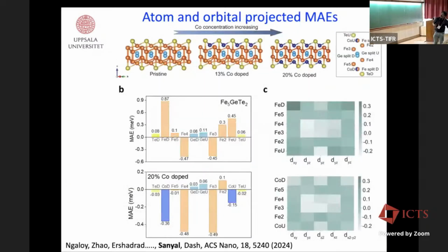We wanted to find out the reason for that, and that's why we calculated the atom-projected magnetocrystalline anisotropy. This is the result for the pristine system, and this is for a 20% cobalt-doped system. You see these positive and negative numbers; overall, if you sum them up, it gives you an out-of-plane easy axis of magnetization. But when you dope cobalt, for example, this iron D site here, when it is replaced by cobalt, instead of positive it goes to a negative direction. So it shows that cobalt doped at this site has an in-plane anisotropy.